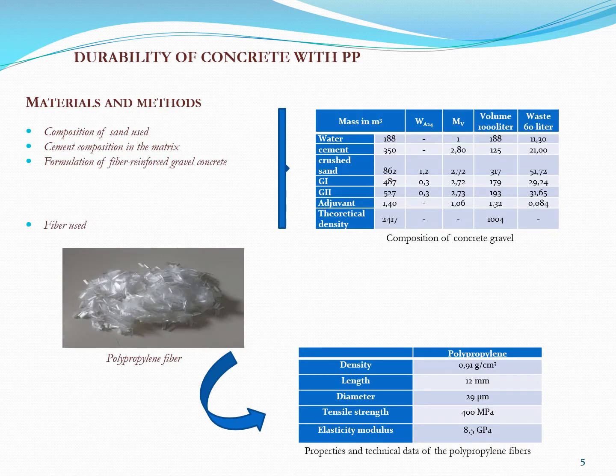In this slide, I am going to talk about the materials and methods in order to study the effect of polypropylene fibers on the durability of cement-based composites. Several experimental tests were carried out in the laboratory. The composite was tested with different volume fractions of polypropylene fiber: 0.05%, 0.10%, 0.30%, and 0.50%.